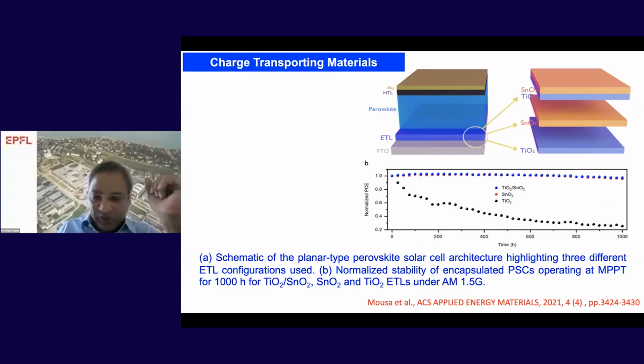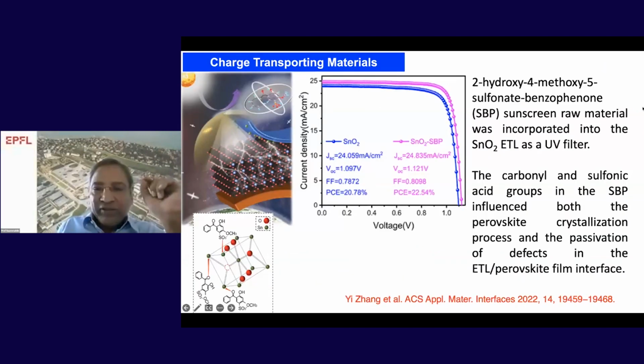This is one example I have taken. Now, the second example is combining a UV filtering compound, typically a sunscreen material. We incorporated it into the ETL layer, that's tin oxide. So this is a reference sample. The power conversion efficiency is 20.78. Now by incorporating the sunscreen material inside the ETL layer, you can see the increase of the efficiency to 22.54% efficiency.